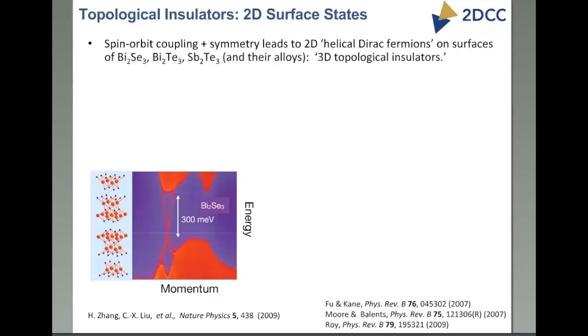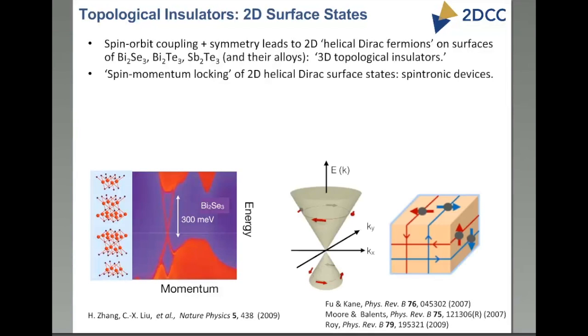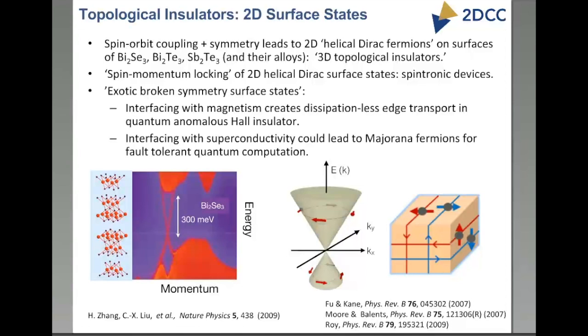And these states have a special property. Just like in graphene, the energy versus momentum is linear. In other words, it's a Dirac-like dispersion. But furthermore, because of the spin-orbit coupling, as you go around k-space, the spin and momentum are correlated with each other. To picture this in a cartoon-like way, look at the cube shown at the end, where I show electrons going around different paths. You see that if an electron is moving in one direction, then its spin is predetermined. If you reverse the direction, then the spin has to reverse. Because of this spin-momentum locking, these types of materials are very interesting for spintronics, and we've shown that in recent studies.